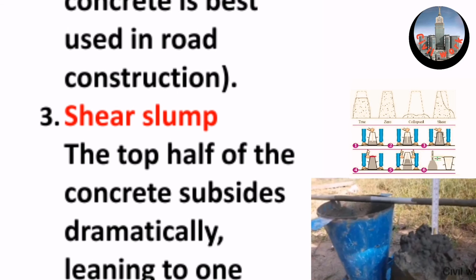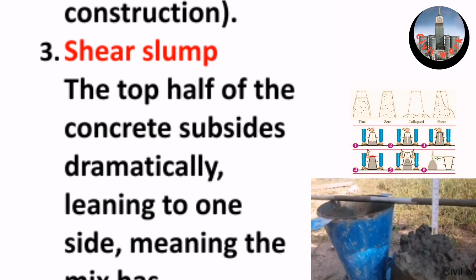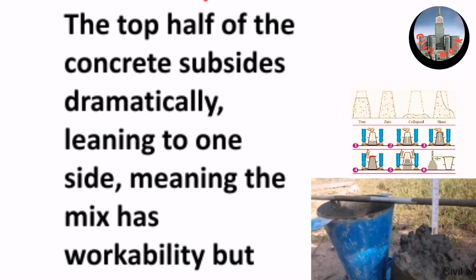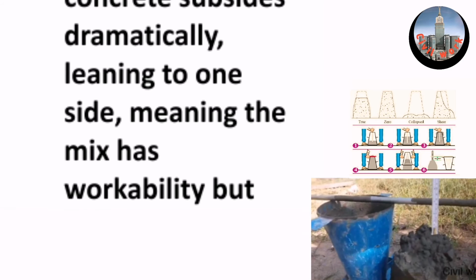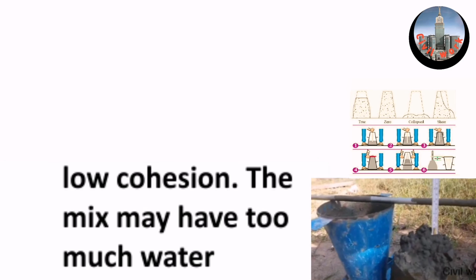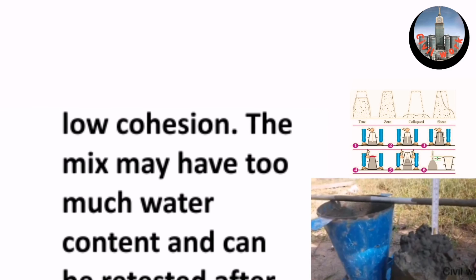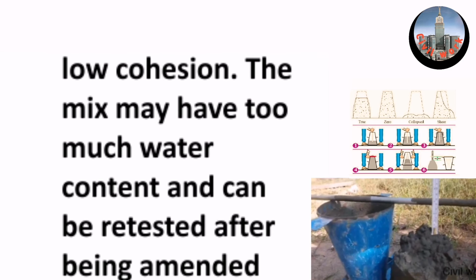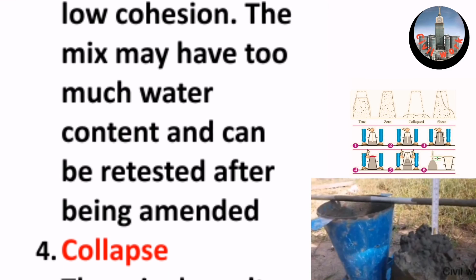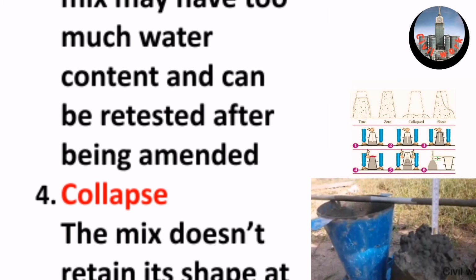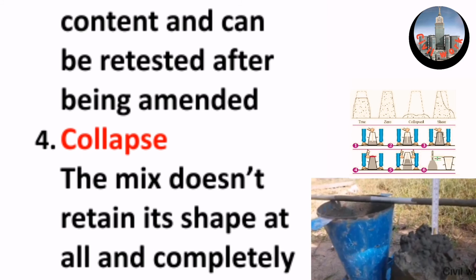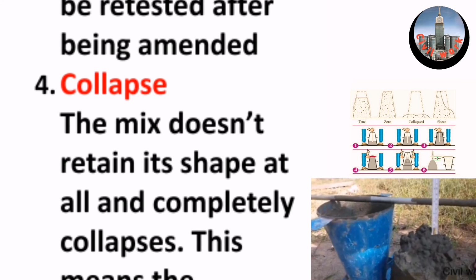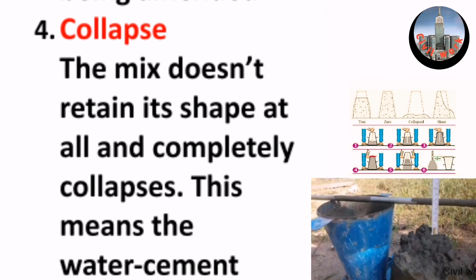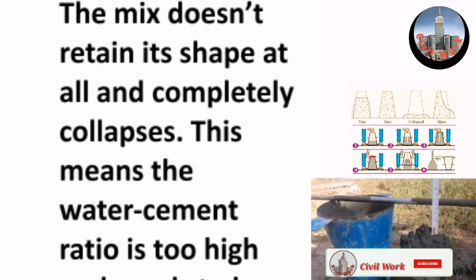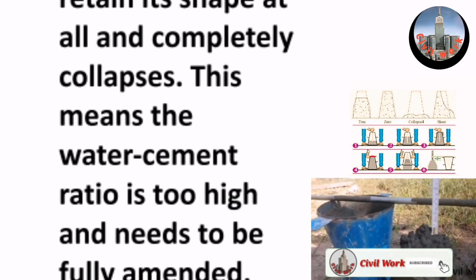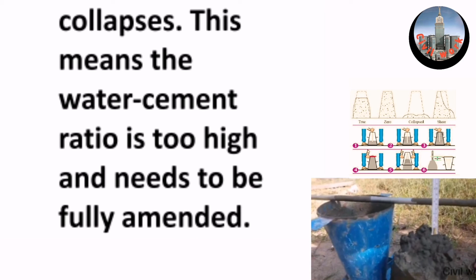3. Shear slump. The top half of the concrete subsides dramatically, leaning to one side, meaning the mix has workability but low cohesion. The mix may have too much water content and can be retested after being amended. 4. Collapse. The mix doesn't retain its shape at all and completely collapses. This means the water cement ratio is too high and needs to be fully amended.